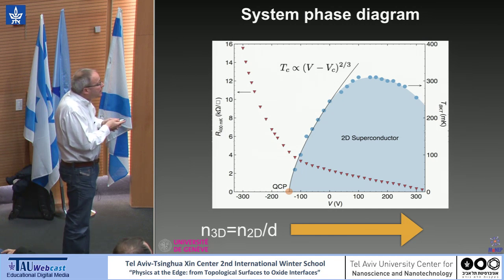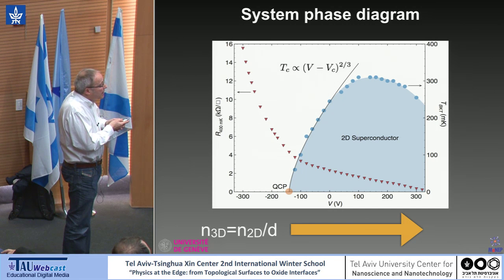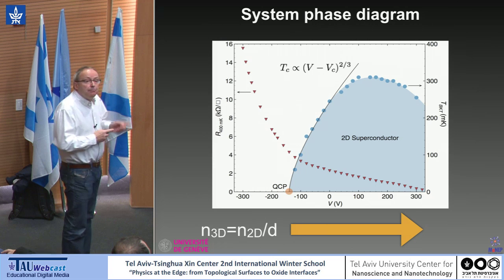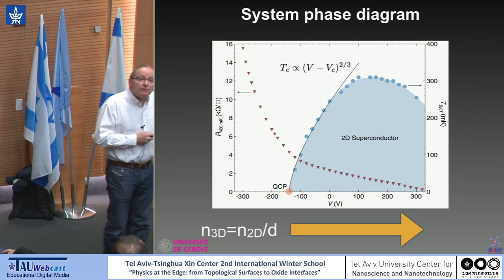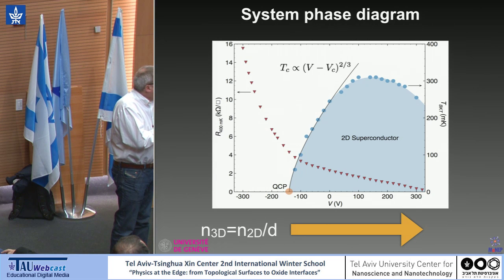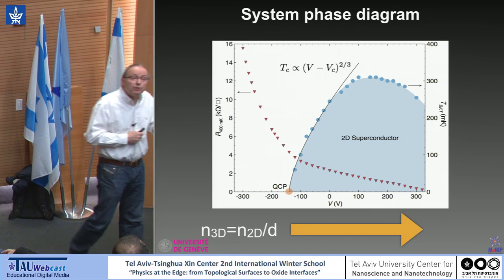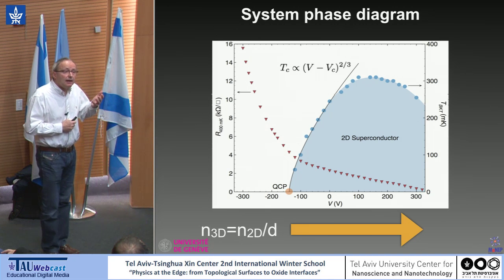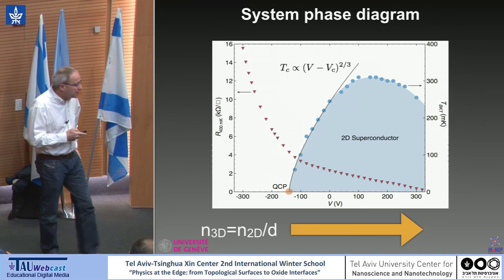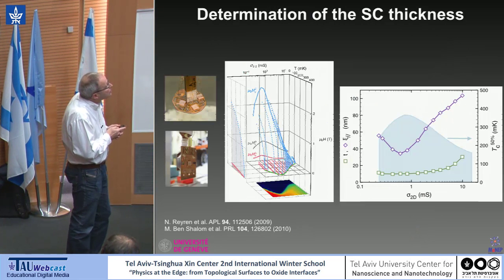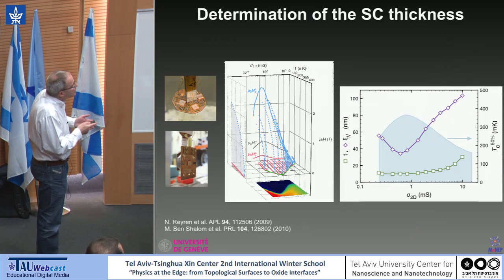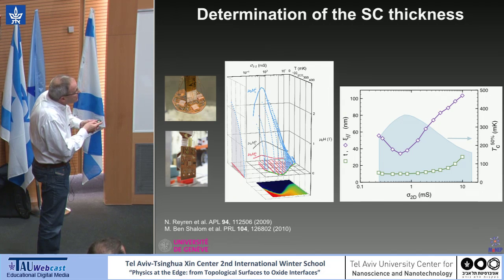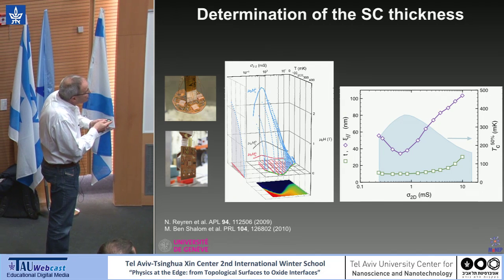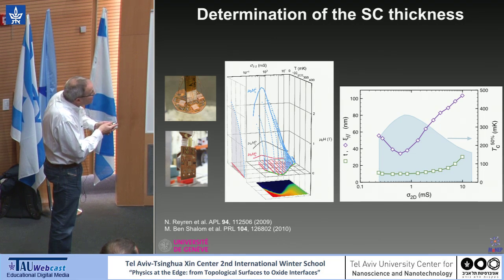We should simply take the carrier density and divide by the thickness. But we have to check what the thickness is as one is crossing the phase diagram. So what we did: perpendicular and parallel field measurements as a function of doping. And this is what you see here. Okay, this is a little bit busy, but this is TC. This is the doping. So TC is here. You see the phase diagram.